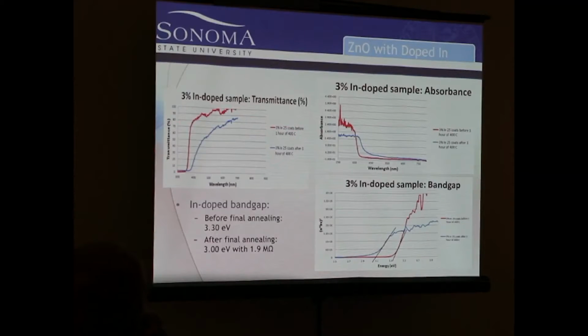So before, I would layer about 25 coats, so it took many hours. But we did it, and we did it at 150 degrees Celsius, and we only annealed them for about 10 to 15 minutes. And so it was a short annealing just to get some of the solvents to stick to the glass a little more, and then as we continue layering it, more of the indium is on, and so hopefully we can have more conductance.